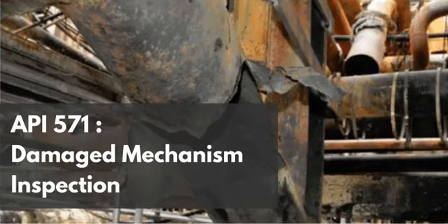So the heat treatment relaxes the microstresses of the localized weld pool, but the massive structural restraint of the unit immediately reimposes entirely new macro-residual stresses as the joint cools back to ambient. Yes. The mechanical physics of the restraint entirely defy the thermal physics of the stress relief. You can have charts proving you held the weld at exactly 1215 degrees for 2 hours and still end up with a weld joint loaded with tensile residual stress. Meaning it's still fully susceptible to carbonate cracking the moment the unit comes back online and the pH hits 8.0,